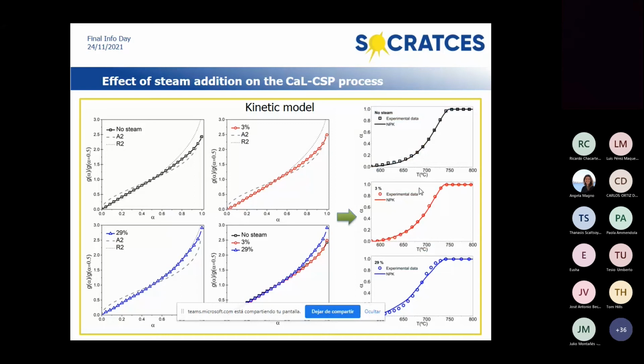And to validate our results, we ran experiments under different conditions, in non-isothermal conditions, with a linear heating ramp, and we were able to reconstruct the curves of the experiment using the kinetic parameters obtained by the non-parametric kinetic method. So the study was validated by doing this.